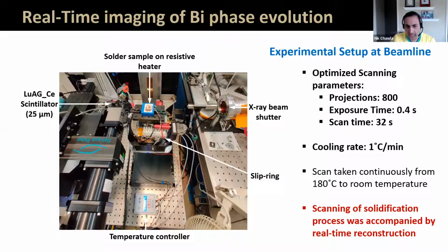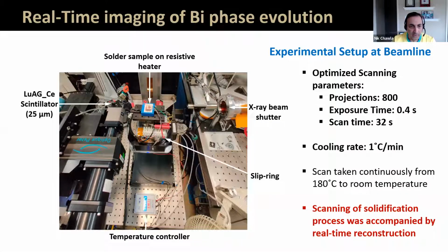Okay. And the scanning was accompanied by real-time reconstruction. So we're scanning and reconstructing, and we're looking at the reconstructed microstructure to determine how the experiment is going. So you actually have the solder sample sitting here. It sits on a resistive heater. Again, the X-rays have to pass through and come out the other end. So this is the X-ray beam, and you have a shutter. And then we have this device that rotates, and you have a slip ring here so wires and things don't get tangled. Okay. And once the X-rays pass through the sample, you have the projection. It goes through a scintillating material, which converts the X-rays to visible light, and then you have a CCD camera on the other side.